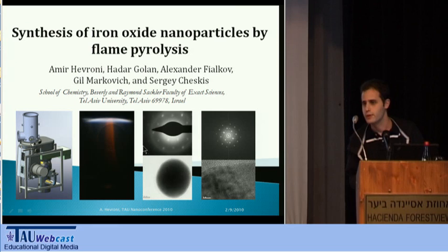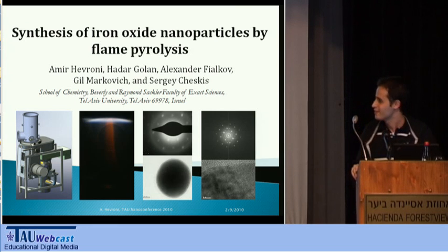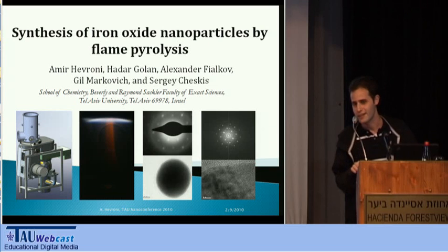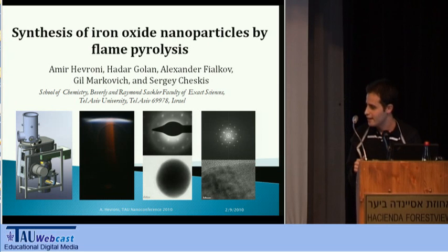In parallel, I've also attempted to develop an alternative method in which I take an inert substrate such as silicon, and I dry out the precursor solution right on it and expose it to the flame front for a few minutes. And the result is actually much smaller particles, on the order of 20 to 50 nanometers, as opposed to these. These are quite large, like 500 nanometers. And these are not only smaller, but also thinner. They tend to form perhaps a sheet-like morphology, I don't know. And they're also highly crystalline as the rest.